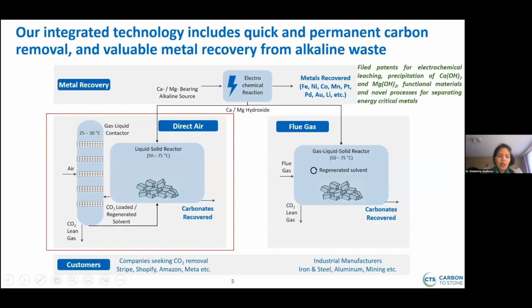So we came up with an alternative solution, and our solution is this. First, we can look at the alkalinity that's actually present in a residue. So we can take a slag material, for example. And some of these slags have a lot of manganese, iron, and other materials. So we could actually put it through an electrochemical process, as I've shown here. And some of the outputs of that electrochemical process are calcium magnesium hydroxide, as well as a solution that is concentrated in the energy critical metals themselves. We can now take the calcium magnesium hydroxide and use that to capture CO2 from air, and we just store the carbonate. So that's our solution for capture and removal with the potential for utilization as building materials.